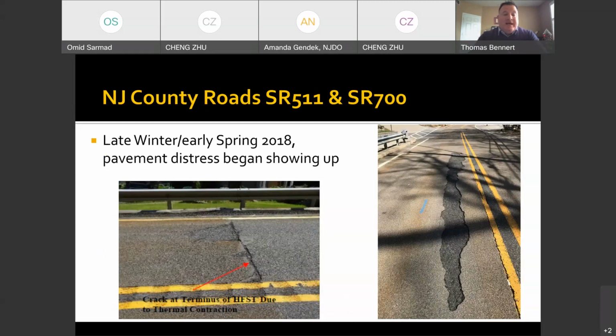You can see at the bottom left, there's again another transverse crack that has initiated at the interface of the HFST and the dense graded. And to the right are some significant delaminations that are occurring. You can even see there's a longitudinal crack right at the edge of the paint that's initiating, because that's the edge of where the HFST was actually placed.